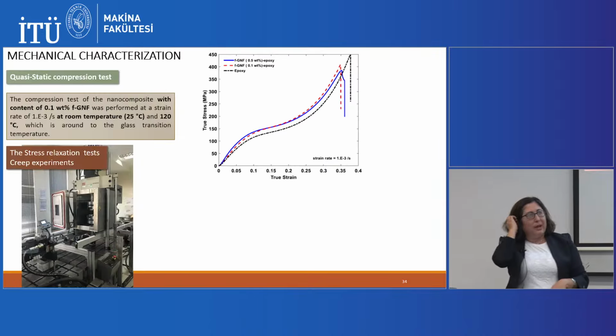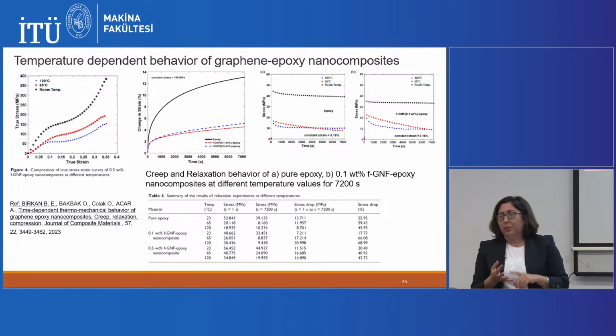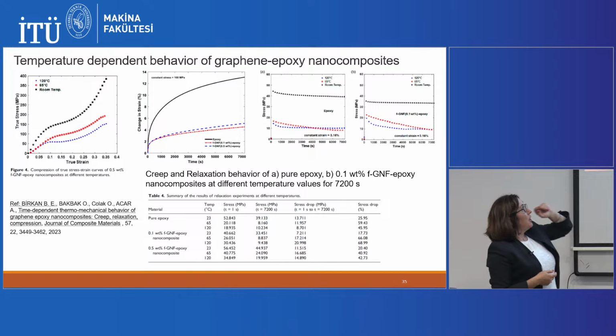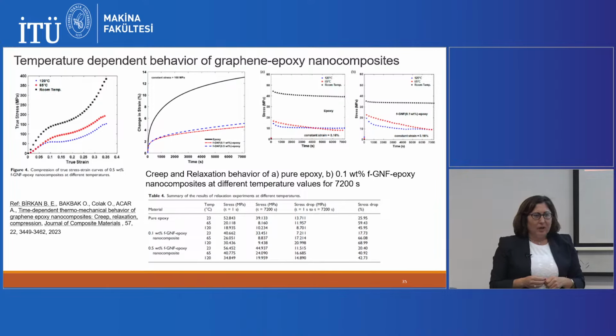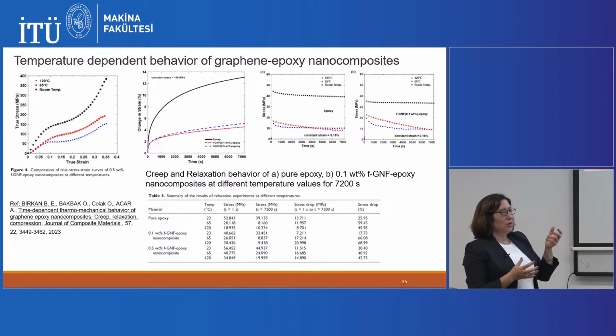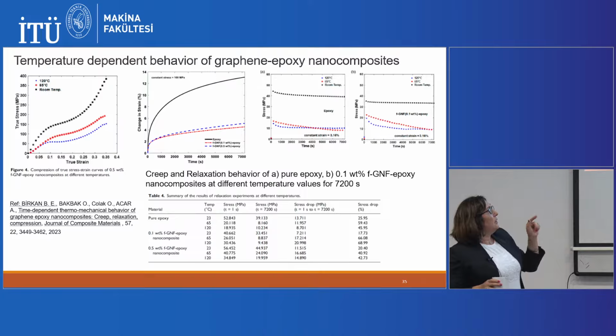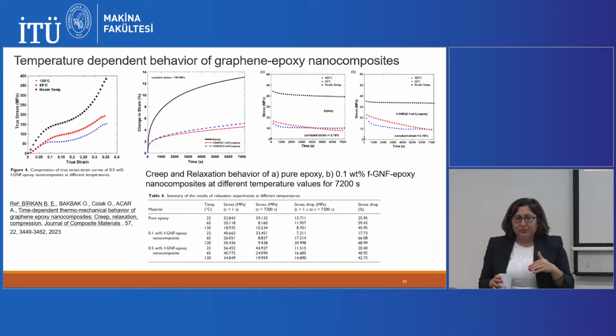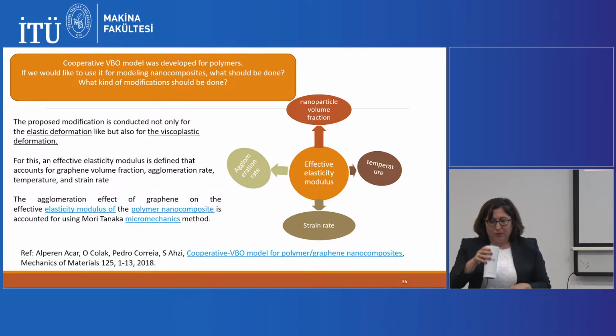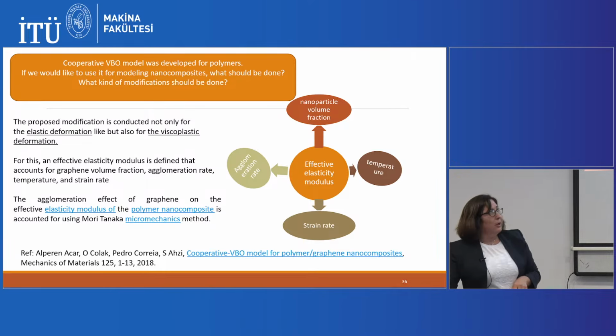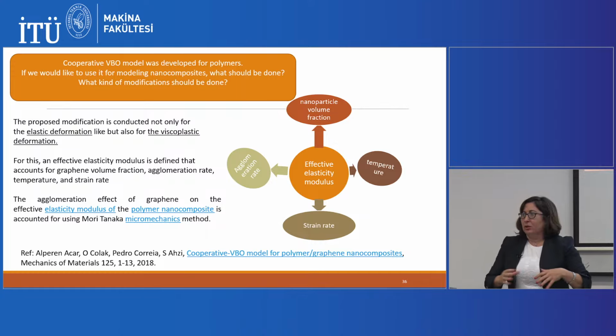Rate dependent and temperature dependent behaviors, and also creep and relaxation. These are a must, olmazsa olmaz. We have to perform these tests so that we can understand how it behaves. For instance, the creep resistance is improved quite a bit. Okan, do you remember how much? 40, 60%? I cannot see it in this figure, but the black one is epoxy, the others are nanocomposites. So it means that deformation is decreasing, which is what we expect or what we want. Sorry about my voice. So these are what we are doing on the material manufacturing and characterization side.